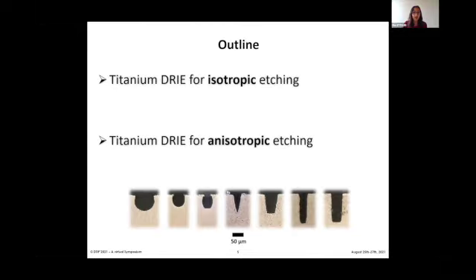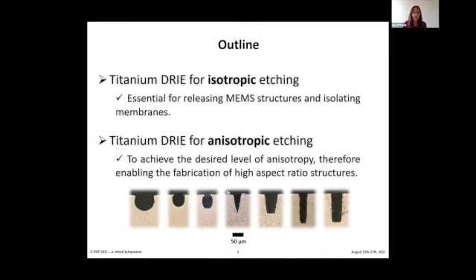Depending on the equipment and the process parameters, plasma etching can be compared to a so-called chemical etching due to the reaction of the chemical species present in the plasma with the surface of the substrate. The substrate is etched uniformly in all directions, which we call isotropy, giving semispherical etching profiles, which can cause problems when etching very small dimensions. And then a so-called physical etching generated by the bombardment of the surface, where species can then be etched. For example, this process can be similar to sputtering. Both ways have benefits and drawbacks according to the application.